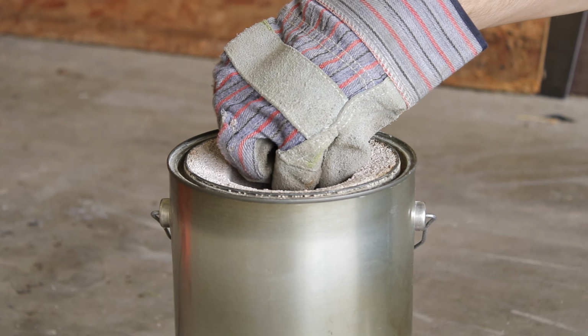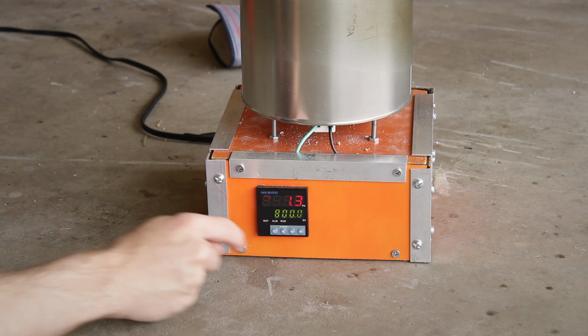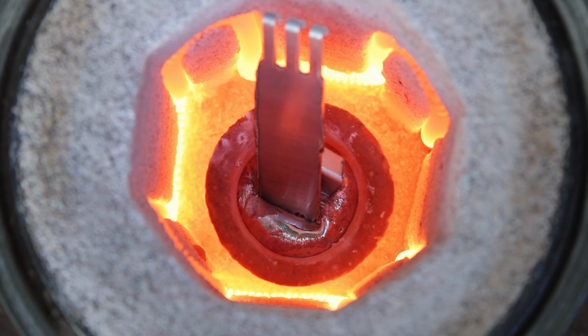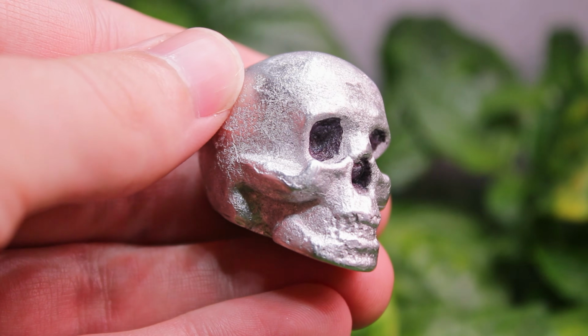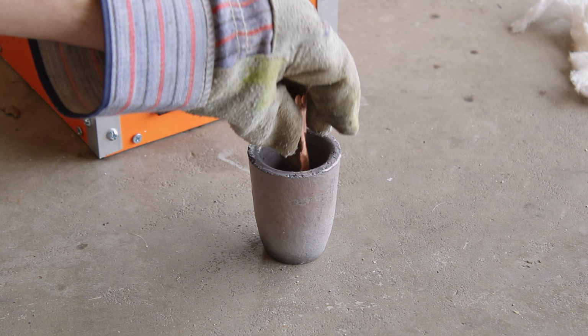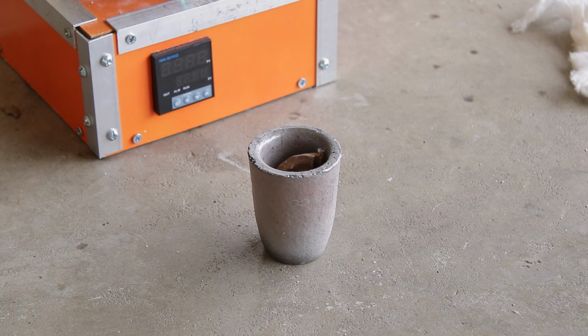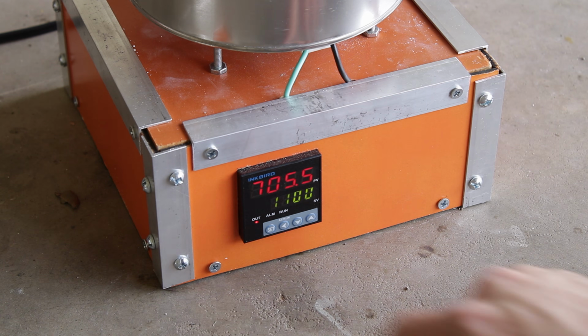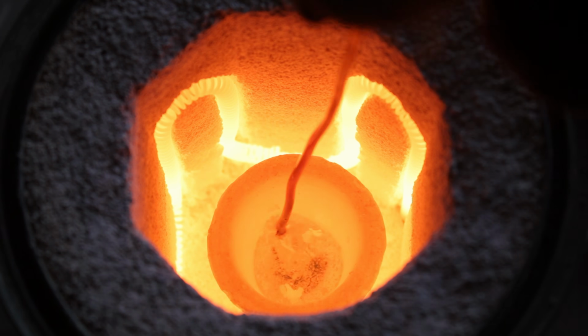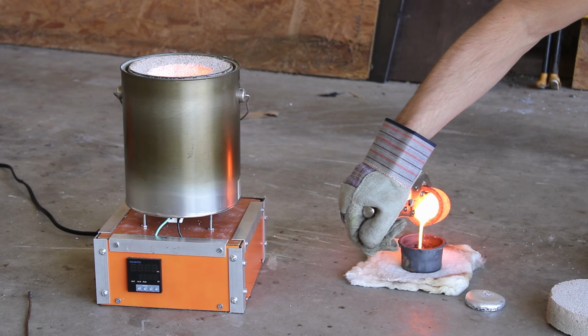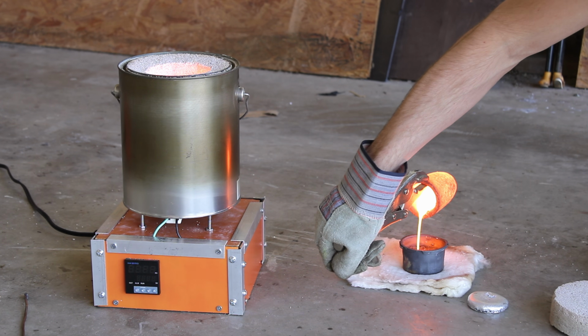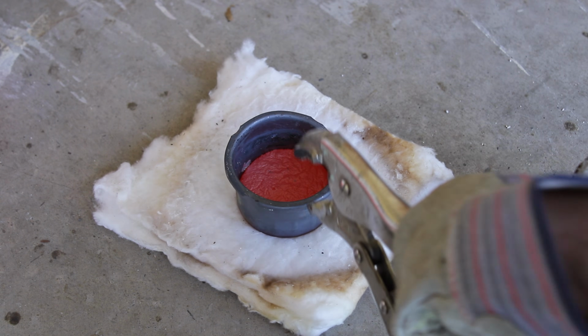By dropping in a crucible and cranking up the temperature to 800 degrees Celsius, this kiln can easily melt large amounts of aluminum in no time flat, making it super handy for DIY metal casting projects. Of course, almost any foundry can melt aluminum these days, so what about a more challenging metal like copper? Well, after setting the temperature to over 1000 degrees, you can see I was able to reduce almost half a pound of this metal to a glowing puddle, and in under 30 minutes as well. Pretty impressive for a paint can.